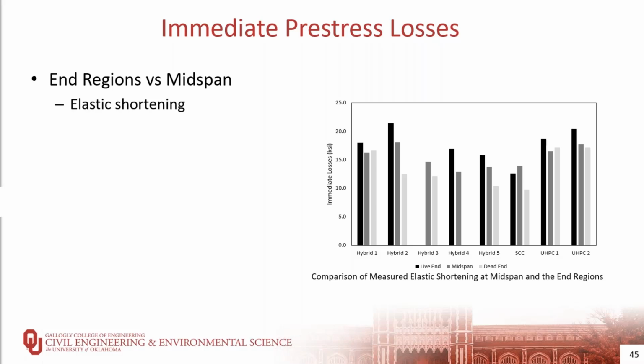The two UHPC girders had a different trend than the hybrid girders. Both girders demonstrated similar elastic shortening at the live end, midspan, and the dead end, suggesting that the compressive forces were high along the entire length of the girder. Meanwhile, the SCC girder exhibited lower elastic shortening at the end regions compared to all other girders. This indicates the lower compressive strains measured from the end regions, aligning with the lower compressive forces at the gauge locations within the transfer length.